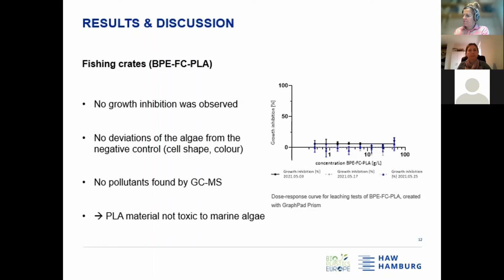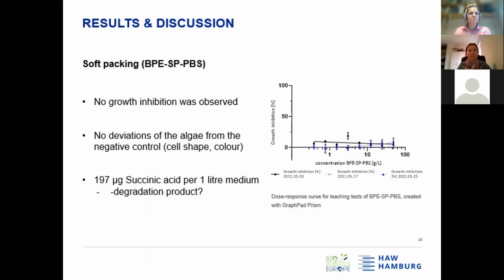And so what we can say about the PLA materials: the PLA materials seem to be not toxic to marine algae. So here are the results from the marine algae test for the PBS-based material, which should be used as soft packing. And like for both PLA materials, we didn't observe growth inhibition and also deviations from the negative control. But we found about 200 micrograms succinic acid per 1 liter medium by GCMS analysis. So succinic acid might be a degradation product of PBS. But in this case, it seems to be not toxic to marine algae.